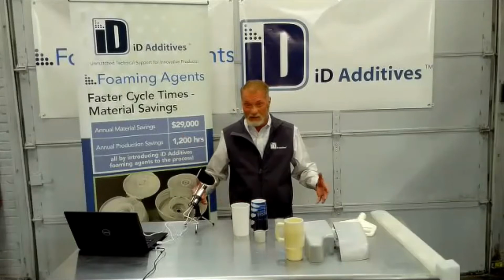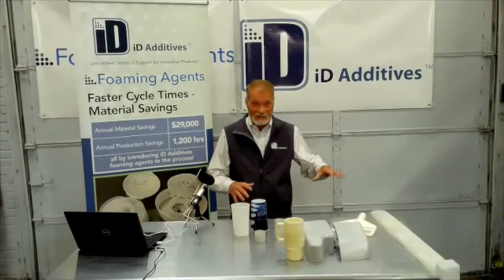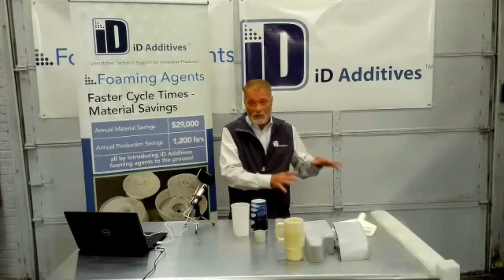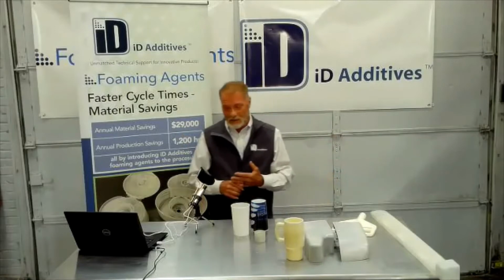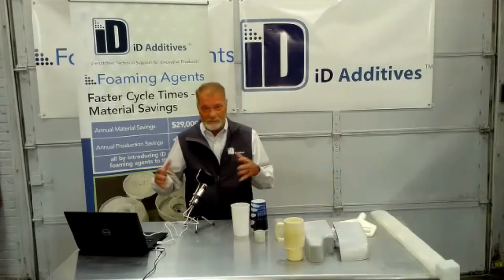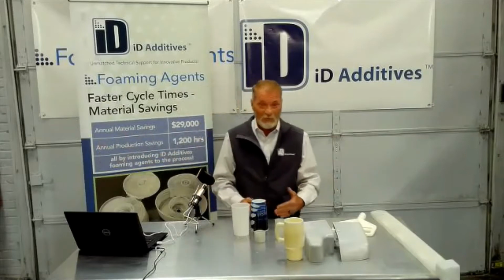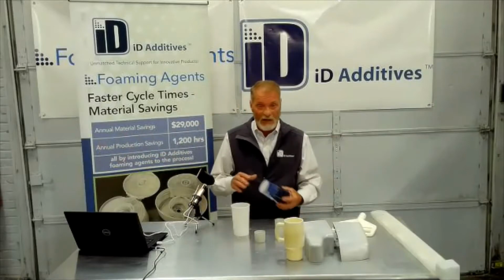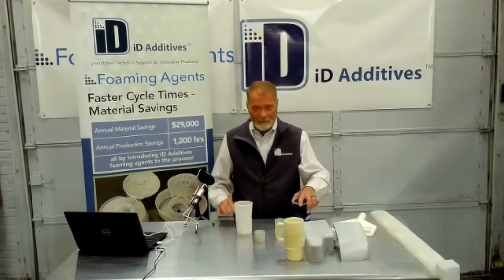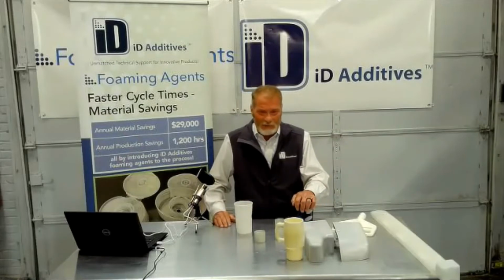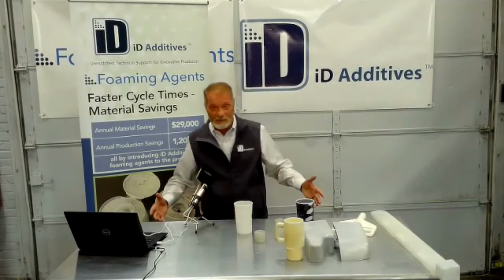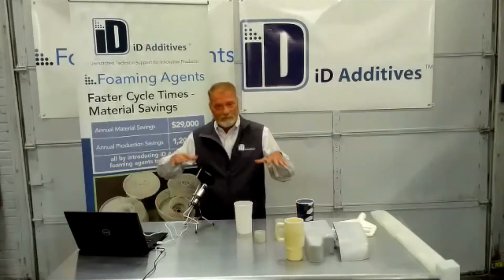They work great together. If foam splays, and you can't really run foam without visual effects that your customer may not like, and the machine just isn't capable of a very high gloss surface, then I would highly recommend calcium. And I always do to our customers. You want to pull that polymer out. You don't want to put too much in there, because then it starts to get brittle. So you've got to watch how much you put in.